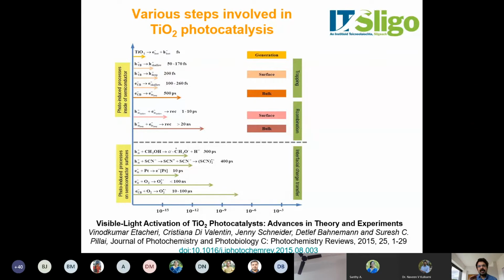We discussed that the electron moves from the valence band to the conduction band, from a lower energy to a higher energy. So what normally happens? The electron from its higher energy will immediately come back. We don't want that to happen because it will reduce the reaction rates. In order to prevent that, we can use a number of trapping agents to trap either the electron or the hole, so that the recombination wouldn't happen, which means that you can use the electrons or holes for various reactions.